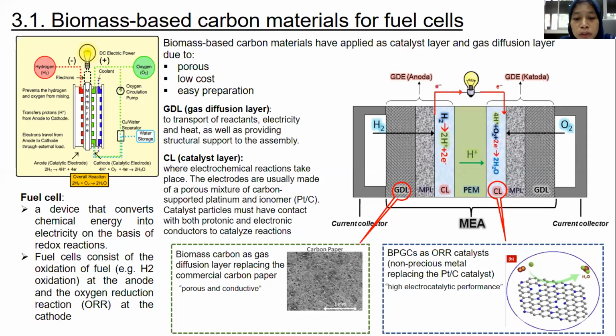GDL is typically a porous carbon-based product, including woven carbon cloth and non-woven carbon paper, while the catalyst layer is a thin layer where the electrochemical reaction takes place. The electrodes are usually made of a porous mixture of nanoparticles dispersed on porous carbon material and ionomer. And biomass carbon has the potential to be utilized as a gas diffusion layer, replacing the commercial carbon paper due to its porous and conductive nature. Biomass-derived carbon materials have also begun to be studied as non-precious metal catalysts for the ORR, replacing the platinum catalyst.